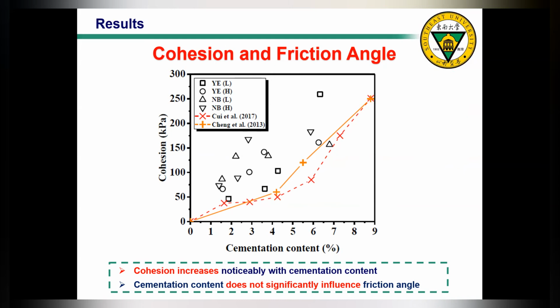And secondly, here I didn't put the friction angle data, but we find that the cementation content does not significantly influence the friction angle, with no significant improvement or reduction.